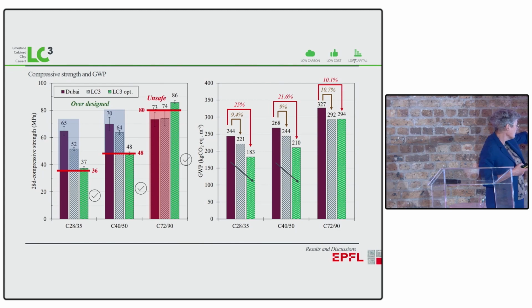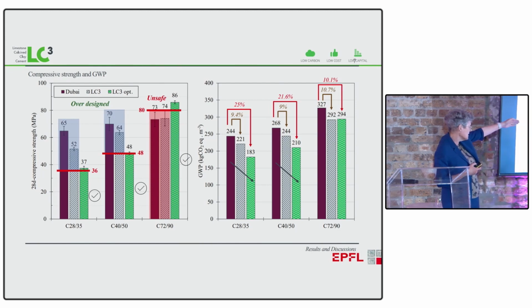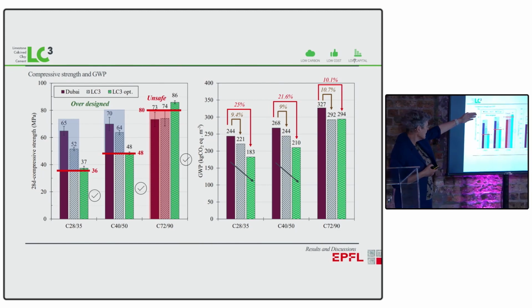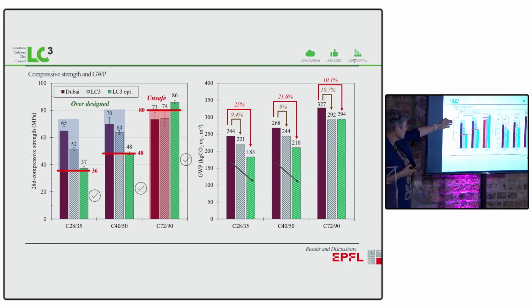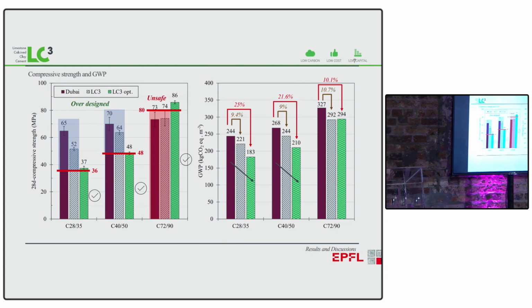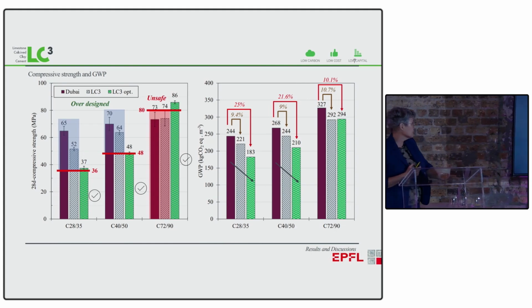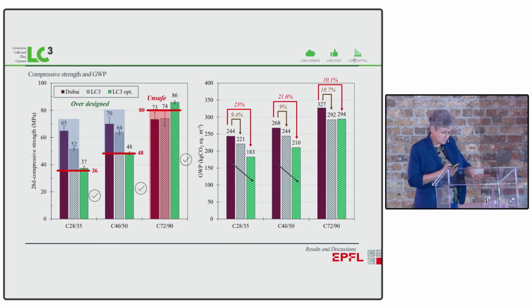So we're now hitting the compressive strengths we need, and in the case of the reference concrete to the LC3 optimized, we can save 25% CO2 for the basic concrete, we can save 21% CO2 for the kind of intermediate concrete, and we can still save 10% of CO2 for the high-strength concrete. And remember, the high-strength concrete they prescribed wasn't actually even meeting the criteria.